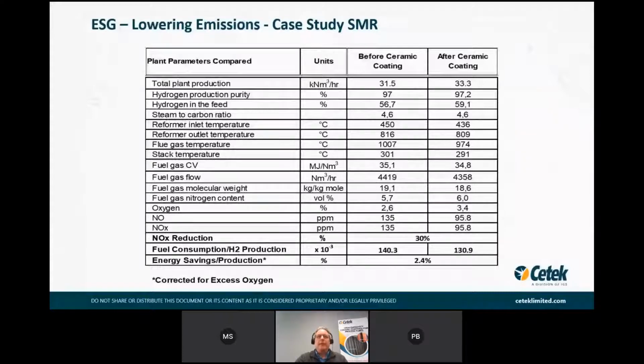Numbers aren't so easy, a little too small here, but if you're looking at flue gas temperature, they're down, stack temperature down, all the things you would expect to see because the coating is doing its job from its high emissivity point of view and of course from the encapsulation side. So when you think about the ratio of fuel consumed for hydrogen production, it should decrease after the coating because you're using less fuel to make more hydrogen. And then that's the win.